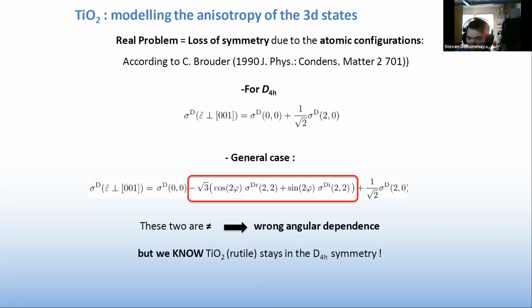But in our general case, you see that we have additional terms here that are caused by the loss of symmetry that is present on all configurations. And so the loss of symmetry that helped us before, like reproduce temperature dependency and subtle effects on the spectra that are observed experimentally, here becomes a problem to reproduce the angular dependence. And we know that TiO2, even if temperature increases, stays TiO2, and so it must have the same symmetry.